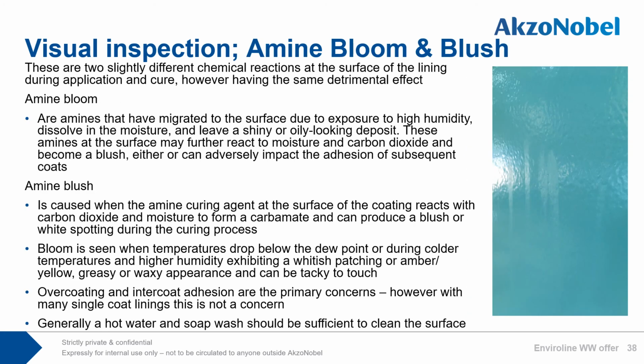Continuing with visual inspection. Amine bloom and blush are two slightly different chemical reactions at the surface of the lining during application and cure, having the same detrimental effect. Amine bloom are amines that have migrated to the surface due to exposure to high humidity, dissolve in the moisture, and leave a shiny or oily looking deposit behind. However, these amines at the surface may further react to moisture and carbon dioxide and become a blush. Either can adversely impact the adhesion of subsequent coats.